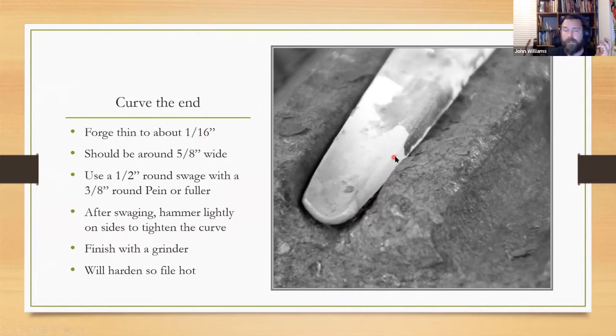The whole reason why you're going to do H13 is you want it to be very thin and still hold up. And H13 is a hot work steel. That's what H stands for, the hot work category of steel. And so you're going to forge it to 1/16 of an inch, and then about 5/8 wide. I might have moved up to a 1/2 inch. You can try the larger one. If it's not a tight enough curvature, then you can just go to the next one, or you can work on the side like I did.